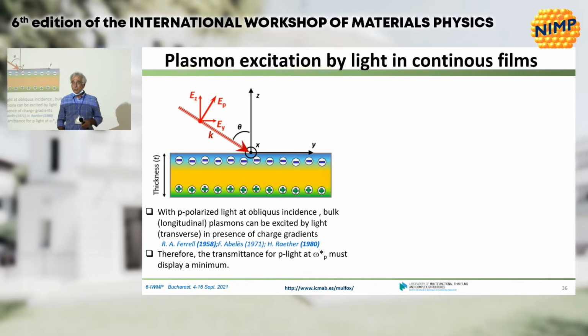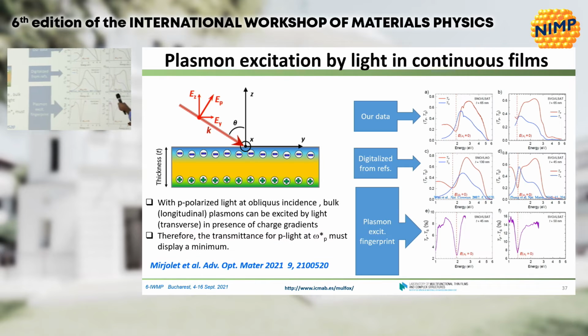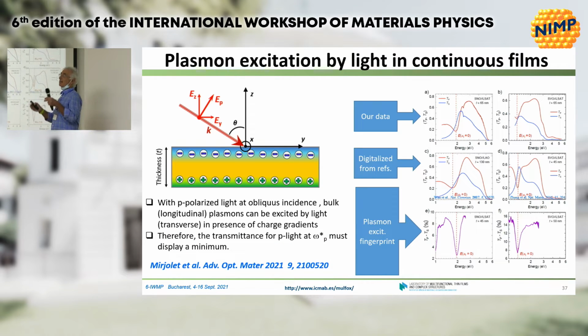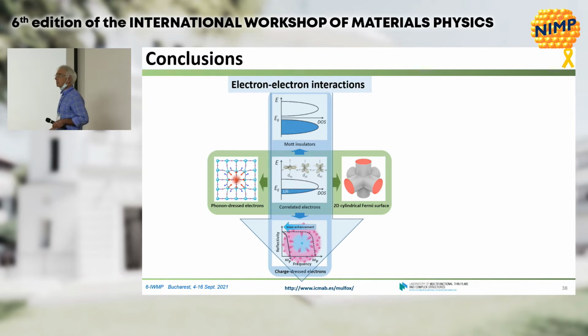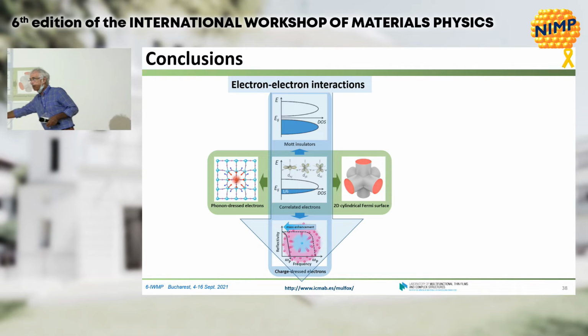So oblique light, P polarized, not S, is going to be able to polarize. And that is what happens. We measure the reflectance and the transmittance for S and for P. And indeed for P, you see a sharp dip in transmission because the vertical component of the p-polarized light excites the plasmon. So you can excite plasmons with light in these films, and now you can imagine doing plasmonics, not at the visible, but at infrared, using these materials, and for many applications that could be very useful.